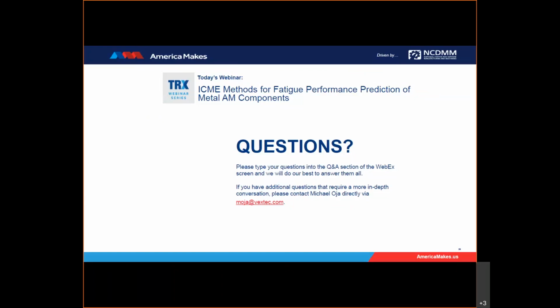Okay, thank you. Let's see, we've got a couple more here. Is it possible to consider the fatigue analysis simulation at very high temperatures, for example, 700 degrees Celsius? I guess I'll take that. If you know what the mechanism is, because you may well get a mechanistic change going on. So for your material, you'd have to go in and put in your material properties for 700C. And if there's a mechanistic change, put it in.